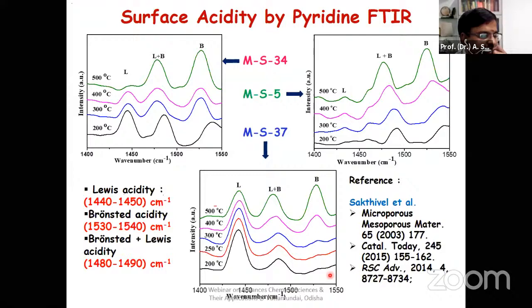The 1540 corresponds to the Bronsted acidic site and 1440 corresponds to the Lewis acidic site. From that we confirm that the peaks are retained even up to 500 degrees centigrade, which means the acidities are very, very strong. It shows the strong acidic character of these materials. That's how this can be confirmed with the materials. So this is the basic way we confirm the surface acidity.